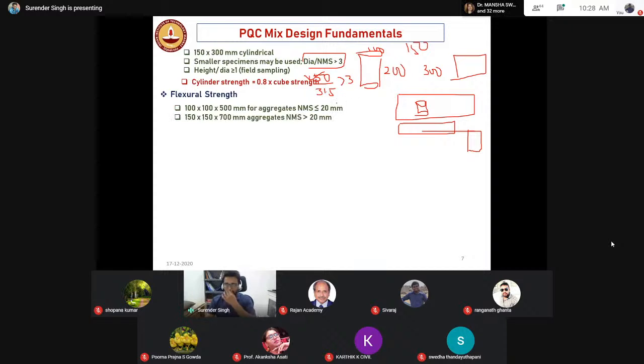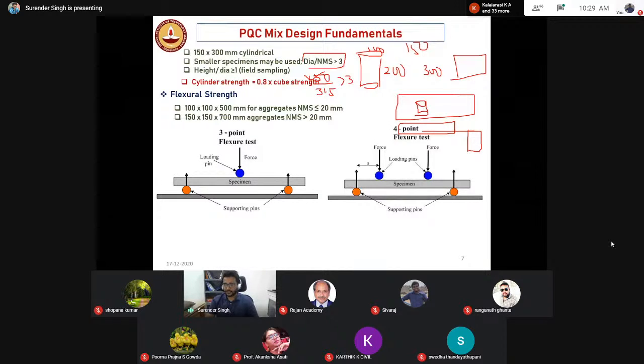If I talk about the flexure strength, normally for the PQC, that is pavement quality concrete, we design for flexure strength. Remember, for the pavement, we always have to decide based upon the flexure strength. This is the flexure specimen, the prism specimen. Similar to the cubical specimen, when your nominal maximum size is more than 20, for PQC it is 20, you have to always go with 150 x 150 x 700 mm. I've seen many research papers where they are going with 100 x 100 x 500 mm, despite their nominal maximum size being 31.5, which is wrong, right?